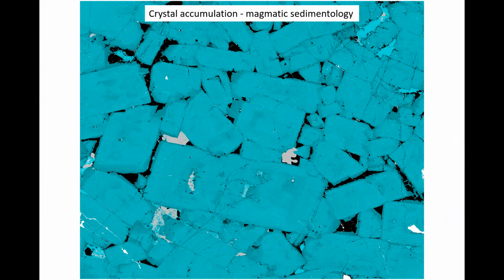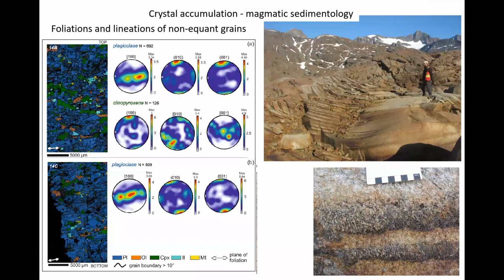What about thin sections? Now, if you've got crystal accumulation, we've got magmatic sedimentology, you generally tend to find your rock looks like a sandstone almost, if you're really lucky. So this is one of the plagioclase-rich layers from the Skaergaard, and we've got clasts of plagioclase with interstitial material here. This happens to be quartz, and we've got interstitial albitic overgrowths. And you can see grain boundaries are formed by the juxtaposition of growth faces. Right, they're just nice euhedral grains, and they've come together and they've solidified. Very, very characteristic. You can also commonly get fabrics, lineations, foliations, and that's because these particles are being moved around and reorganized by magmatic currents.